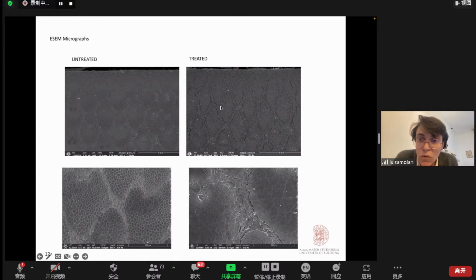and we see that for the treated samples we had a sort of texture. There are some cracks between the islands of the fibers and the parenchyma cells. I hope that you can see, but the difference between the two is evident, and this is something that could also explain the differences in the Poisson ratio, because we do not see damage in the direction of the fibers, but we can see damage in between fibers and the parenchyma. So this could bring more or less the same behavior in the direction of the fibers, but something different in the direction orthogonal to the fiber itself.